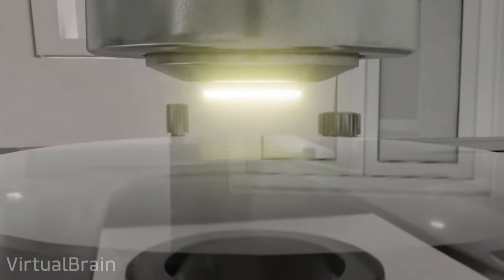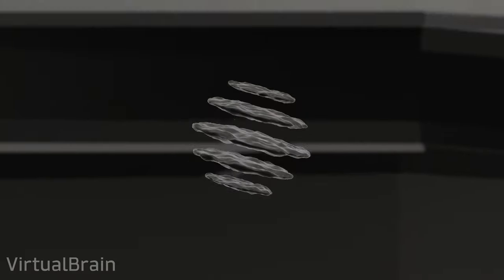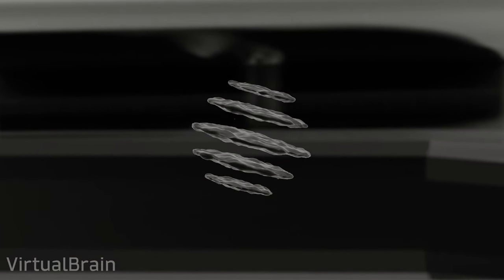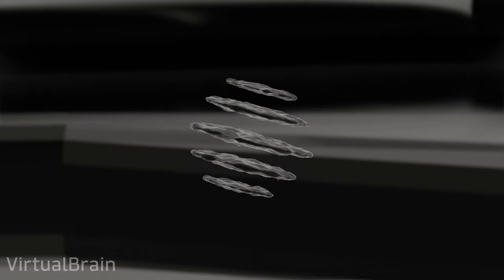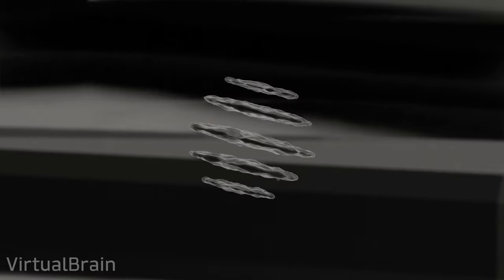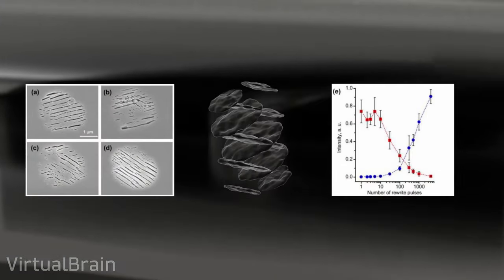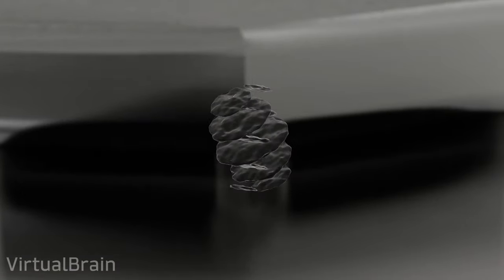Understanding this, if we control with extreme precision the polarization and intensity of the light pulse concentrated in the crystal, we can induce chemical reactions that naturally create microstructures in the form of grids, managing their size and orientation at will. And not only that. Perhaps the most impressive thing about this method is that if we hit these microstructures again with light pulses with different characteristics than the pulse that created them in the first place, those microstructures can be overwritten, overcoming the limitation of the previous method.